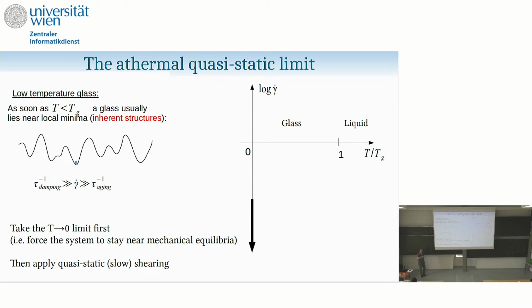The only way to have something interesting occurring is to shear. And when you start shearing the system, now you force the system to change. And so the athermal quasi-static limit is the idea that you take first T to 0. And when I say T to 0, again, I'm saying that I will only look at local minima of the potential energy landscape. I bring the system to a local minimum, and then I will apply shearing at a very slow rate.